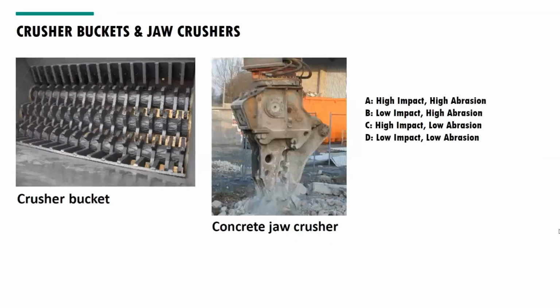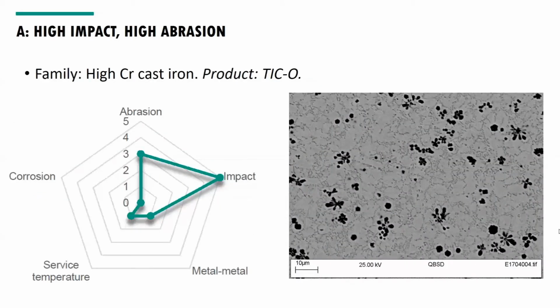And the answer is... Yeah, so well done to everyone who guessed A. It's a high impact, high abrasion type material. And you can see over here we've got an austenitic matrix with titanium carbides dotted in there. So the austenitic matrix provides the toughness required for good impact resistance. And then the titanium carbides are very hard, which provide the abrasion resistance. So we have a good product there, which is good for combined abrasion and impact. Next slide, please.